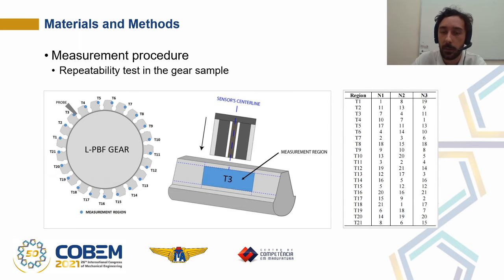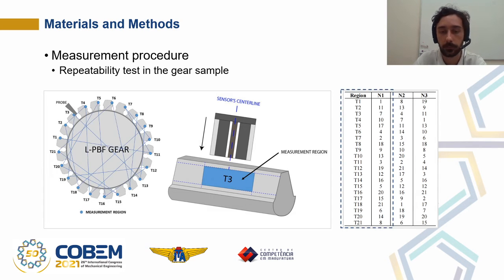In order to estimate the repeatability and reproducibility of measurements with the Barkhausen noise sensor, the experimental procedure was developed to observe the variation due to the measuring process when the operator measures the same part several times, and to observe the variation due to the method itself by comparing the results of the 3 different operators. First, in the repeatability test, the operator measured the 21 tooth gear sample in 3 series of test repetitions, N1, N2, and N3. To also ensure the randomization of measurements, the order of measurement of the flanks was randomly defined for each operator.